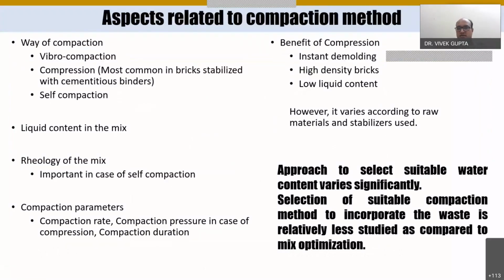So these are the other aspects related to compaction method. Like in the literature, there are three different methods, and the most common in bricks stabilized with the cementitious binder is the compression technology. Then liquid content in the mix is another important aspect we have seen in the previous slides. Then rheology of the mix is also important, especially in the self compaction mixes. And the compaction parameters, like the compaction rate, the compaction pressure in case of compression, and the compaction duration. In some of the literature, they have worked on long compaction durations also, up to certain minutes. However, in the industry, we generally go for the 10-second compression.